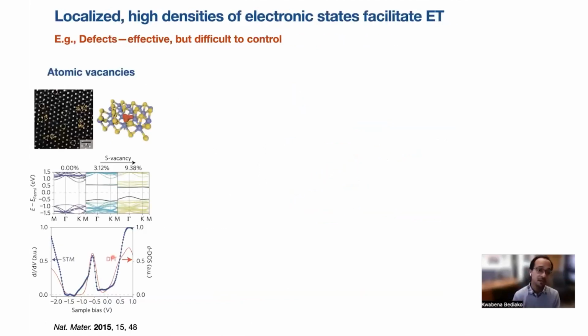And there are a number of examples where we basically managed to facilitate interfacial charge transfer using this general idea. One is in the exploitation of defects. So atomic vacancies, for example, in this case, molybdenum disulfide, create mid-gap states, defect states in the material that show up as localized electronic states if you were to measure the density of states indirectly using, say, scanning tunneling spectroscopy. And these states are implicated in the hydrogen evolution behavior and activity of the basal plane of MoS2. So usually the more defects you have, the more active your material is.